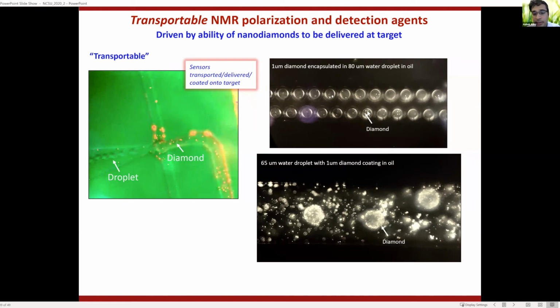number of these nanoparticles. You can also go to the opposite regime where, as here, we've taken a microfluidic droplet of water and oil, and by controlling the surface hydrophilicity or phobicity, we have been able to dress the droplet with nanoparticles of diamond. So this is a water droplet with nanoparticles dressing its surface on the outside. And you might ask what's interesting about them.